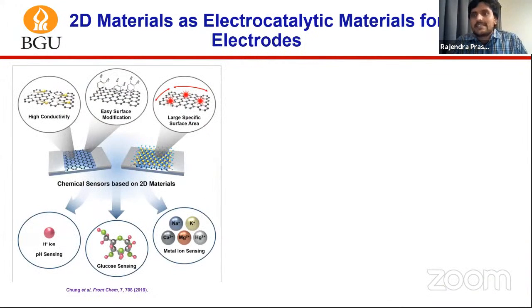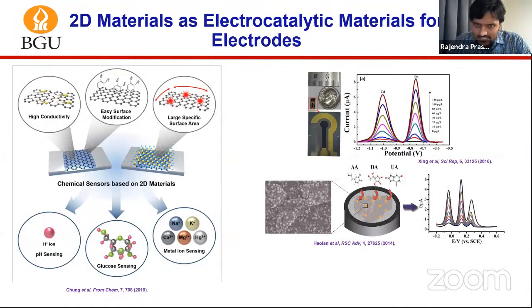In order to overcome the challenges of interfering species and to increase specificity and selectivity, nanomaterials, for example 2D nanomaterials, have been used widely because of their advantages and better characteristics, for example, high conductivity, easy surface modification, and large surface area. In the recent past, this kind of electrode modification has also been used at the macro scale, but they use a photolithography technique to pattern and modify microelectrodes on gold electrodes. Also, the 2D material MoS2 has been used for the detection of analytes, for example, ascorbic acid, dopamine, and uric acid.